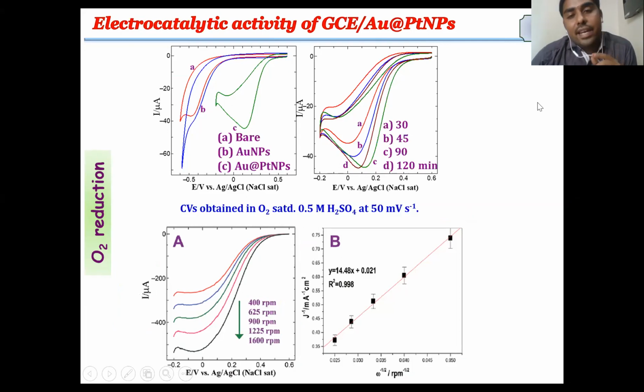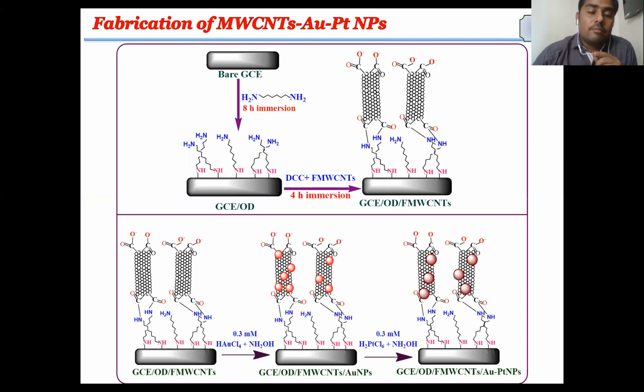So by varying the different compositions, the 90-minute deposition shows higher catalytic activity, and with the help of the KL plot, the Koutecky-Levich plot, we find that it is a 4-electron transfer mechanism, and there is a formation of water from O2.